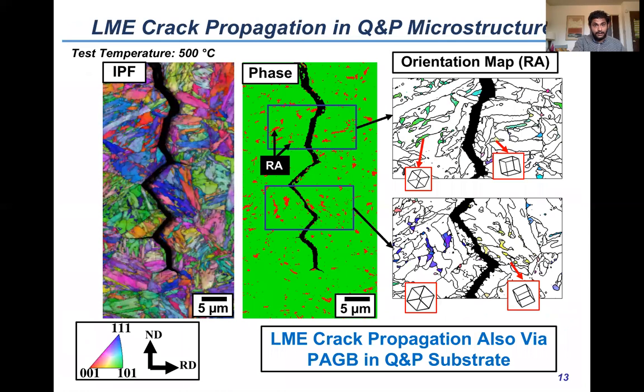Now, what about the Q&P microstructure, which is different from the martensitic microstructure? So here is the EBSD IPF of the crack in the Q&P microstructure. The phase map says that there was not only martensite, which is the green part, there are also these red phases. The red is the retained austenite in the Q&P microstructure. We carefully looked into the orientation of the retained austenite on two sides of the crack. So here is the orientation map of the retained austenite, and what we find is that the retained austenite on the two sides of the crack have different orientations. Now, what does that mean? It means that the crack in the Q&P microstructure again followed prior austenite boundaries.